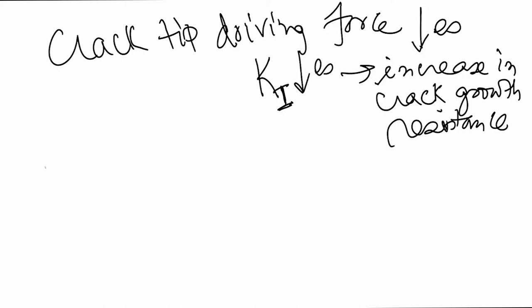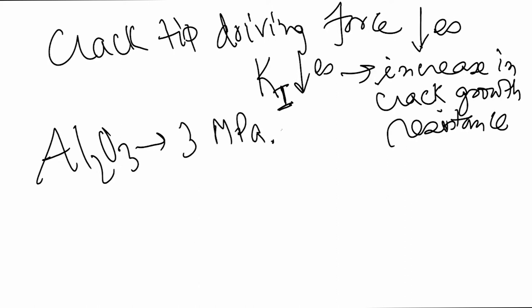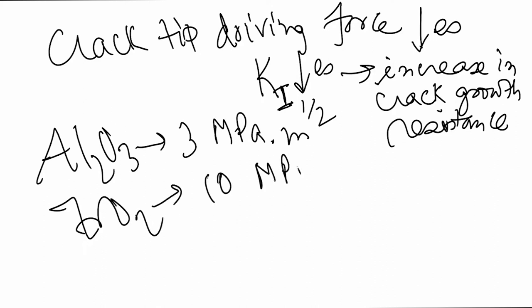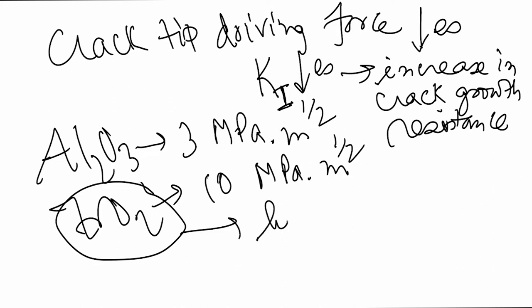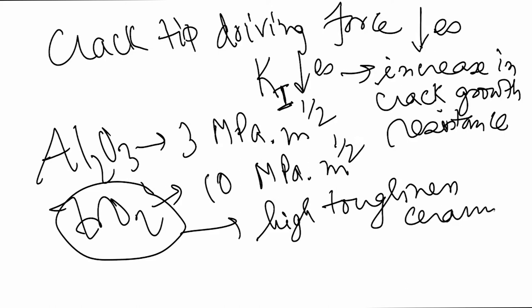Okay. So, for example, alumina, their fracture toughness is around 3 MPa square root meter. For zirconia, their fracture toughness is around 10 MPa square root meter. So, that is why zirconia is one of the materials which is considered a high toughness ceramic. Okay. So, toughness is essentially a measure of the crack growth resistance. Typically ceramics are known for their inherent brittleness, and if fracture toughness is increased, then the application of the ceramics also would widen.